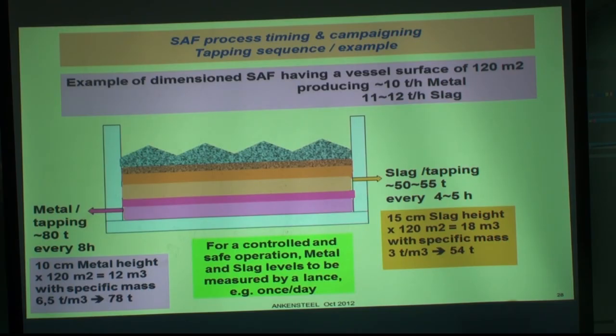Metal resistance is much lower than slag. So you have also maybe, but maybe not, a temperature difference between slag and metal, but we have a big decrease of resistance. Is there no difficulty to penetrate the lance into the ore? No. I think there may be if you have a kind of sintering of the solid, then it may be, yes. Even though it can be possible. For me, it is possible, yes.